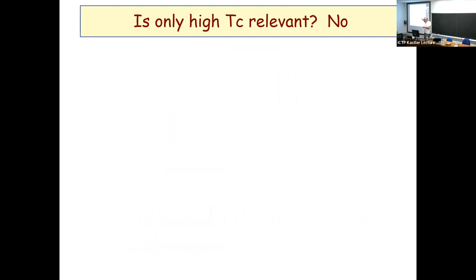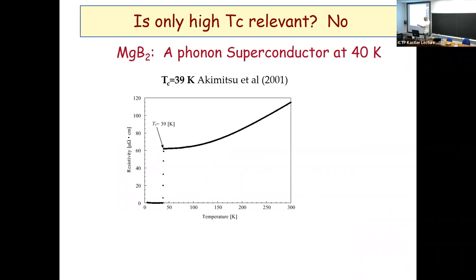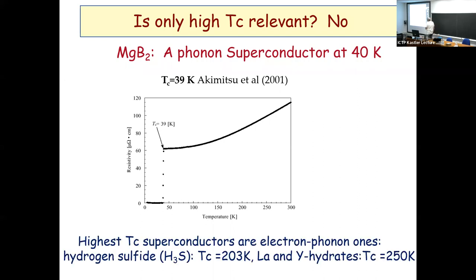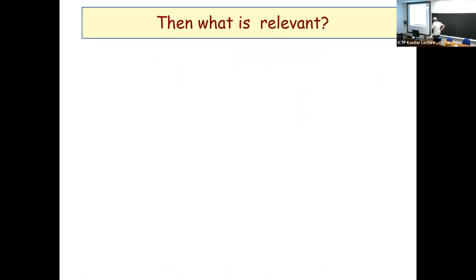The question is this: is high TC really relevant for what is called new non-phononic superconductivity? The answer is definitely no. There is one slide which I borrowed some years ago from Geert Bloomberg. This is MgB2, wonderful superconductor, nice phonon superconductor, TC is 39 Kelvin. Let's not forget that the highest TC superconductors are hydrides under pressure, and hydrogen sulfide has TC larger than 200 Kelvin. And the record, I guess, is really now close to room temperature, depending on in which room you are. But then the question is, what really is relevant?